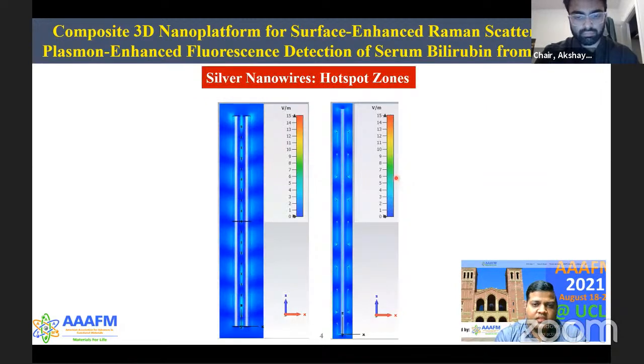As we can see here, these are two of the many configurations that we are particularly interested in. In this configuration, the nanowires are intercepted by nanoparticles. And here the case is opposite. The nanowire is sandwiched between two nanospheres. In fact, these nanospheres represent intersection points or junction points in our analysis.